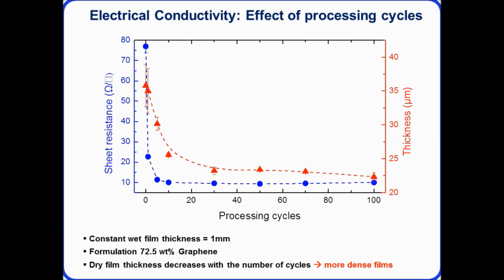So if you want to go to much thinner conductive films, you might need to process the material for 100 cycles. However, you obviously need to think, are there any drawbacks with the throughput? So maybe if we're processing for such a long time, the graphene production rate will considerably drop. So it's about finding the right balance between process cycles and your actual final product performance.